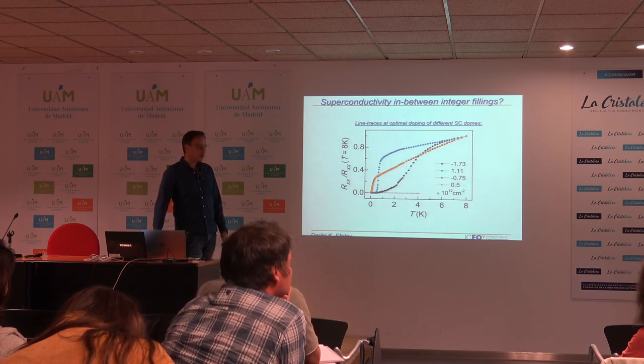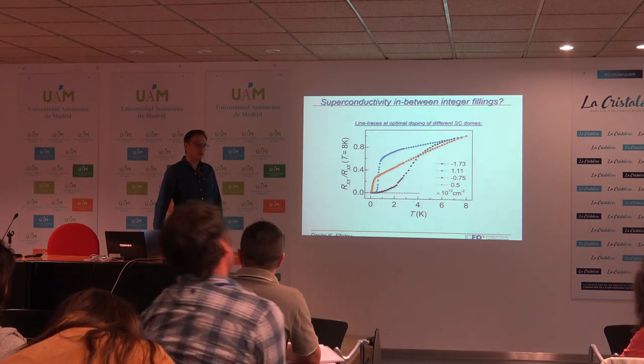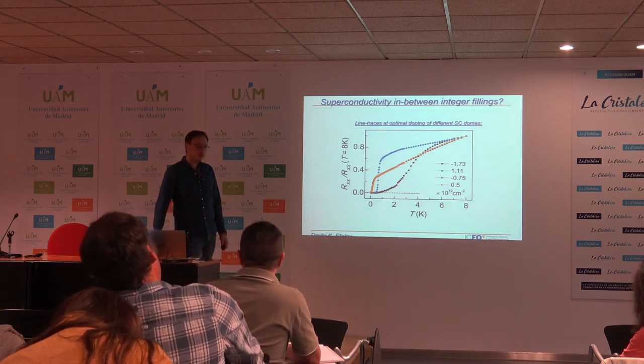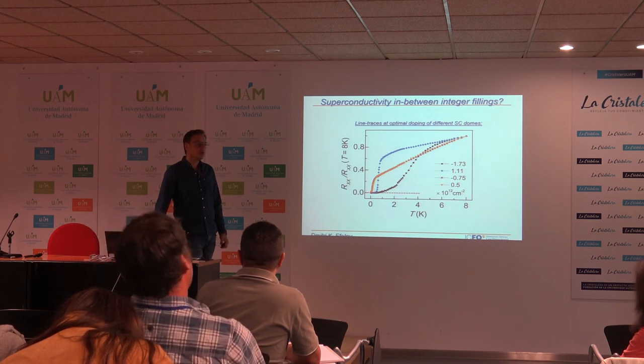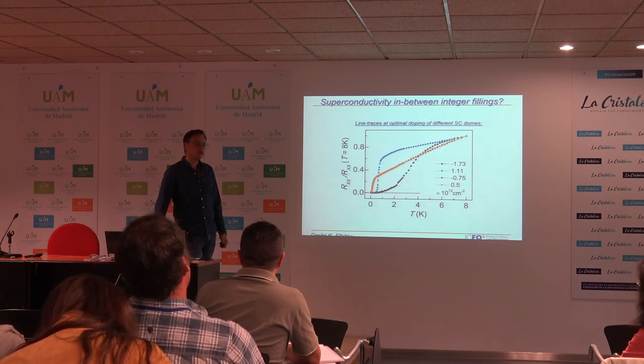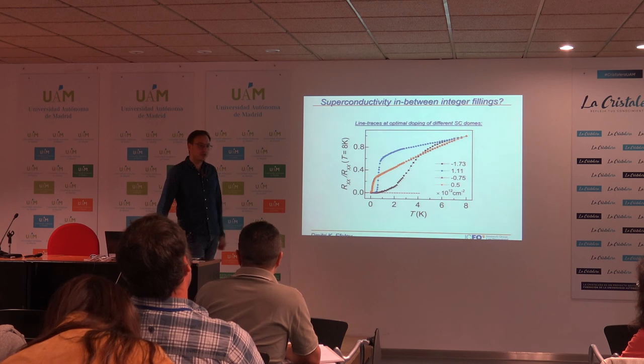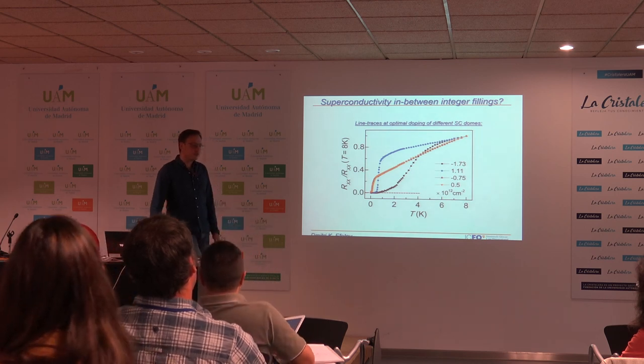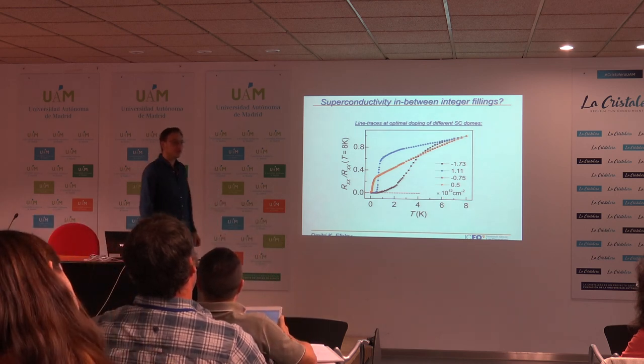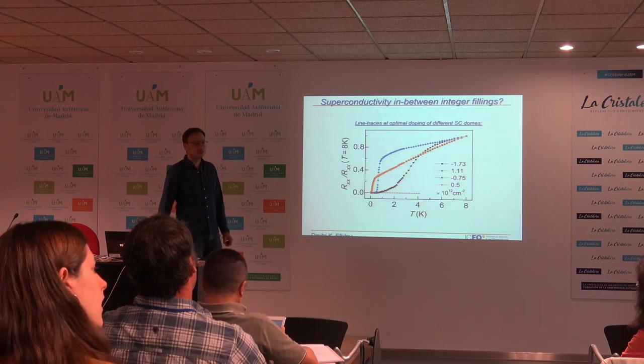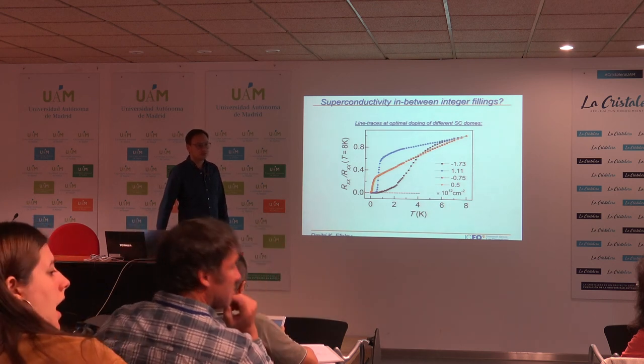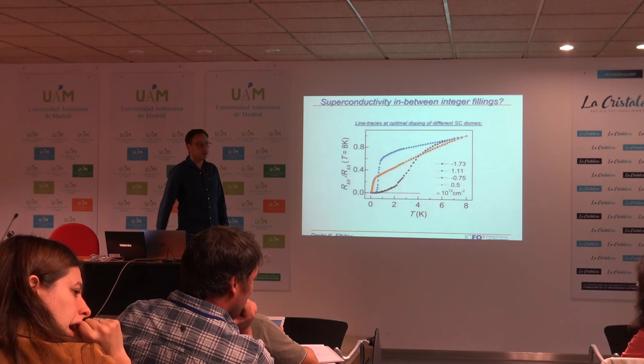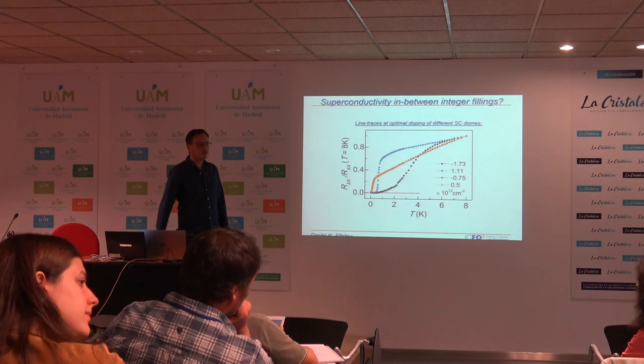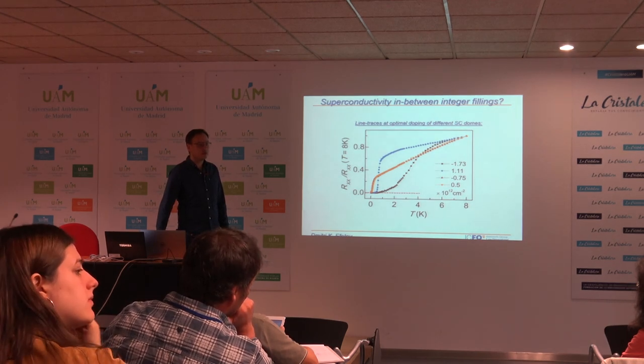In our case, we now have five devices which all show a charge neutrality point gap, but we don't think it's aligned. Again, it's really hard to prove it's aligned. We try not to align it, but almost every device shows a charge neutrality point gap without us trying to align it to the hBN. And the gap is always more or less the same size. It varies between 0.5 meV and 1.5 meV.